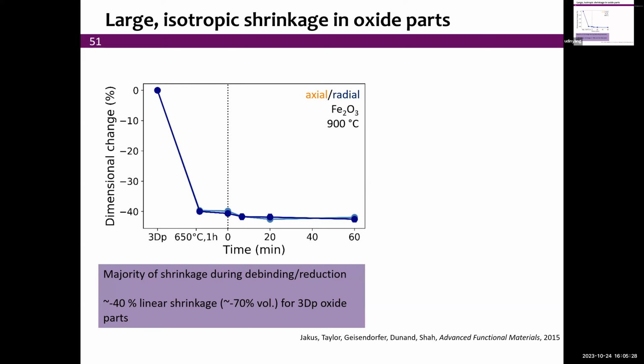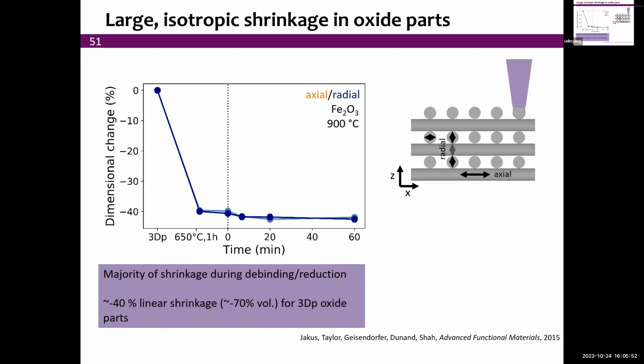Previously, both the axial and the radial shrinkage are exactly the same. In fact, that's very important. It means that this is a homogeneous shrinkage, which is why we don't warp the material. Everything is very, very homogeneous and uniform in all directions. So that 40% linear shrinkage, which is about 70% by volume, is uniform. And as I said, having uniform axial and radial shrinkage means that we don't warp. Warping would occur, for instance, if the axial shrinkage was more than the radial one. And so that explains why we get this extremely high fidelity in the shape while shrinking dramatically.